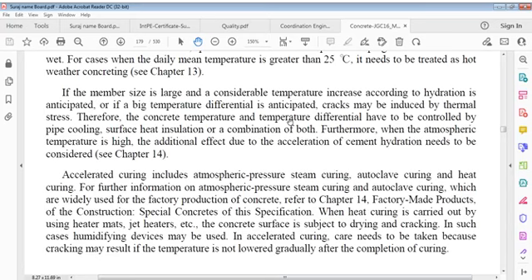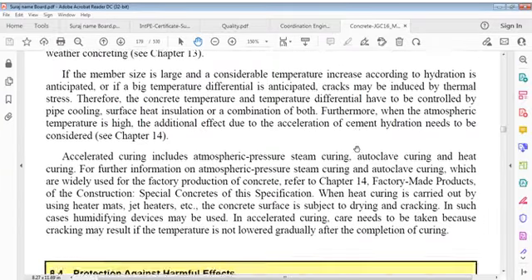If member size is large and a considerable temperature increase according to hydration is anticipated, or if a big temperature differential is anticipated, cracks may be induced by thermal stress. Therefore, concrete temperature and temperature differential have to be controlled by pipe cooling, surface heat insulation, or a combination of both. Furthermore, when atmospheric temperature is high, additional effect due to acceleration of cement hydration requires to be considered.